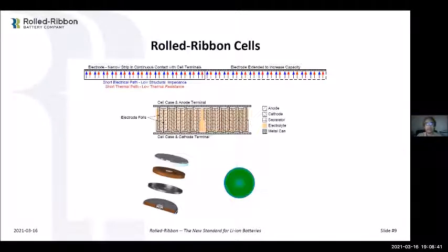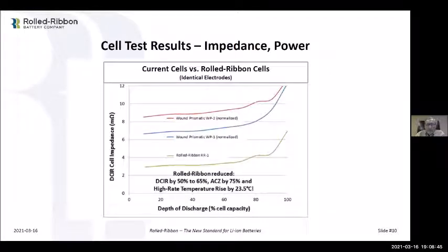Okay. And like I say, you see it in the test results. It comes out in the DCIR. DCIR is actually a measurement of two components. And remember I said, here's a test, identical electrodes. So we use exactly the same, so the electrochemistry is behaving the same, no difference. They're cut from the same lot, made from the same roll. So you have two parts to DCIR. You have electrochemical resistance, and then you have the structural resistance, which is the metal contact. So you can see from here, the only difference roll ribbon is making is structural. It's not changing the electrochemical, right? That's a given, because they both have the same. And so the structural impedance here is much lower with roll ribbon by having that massive edge in continuous contact with the entire band.